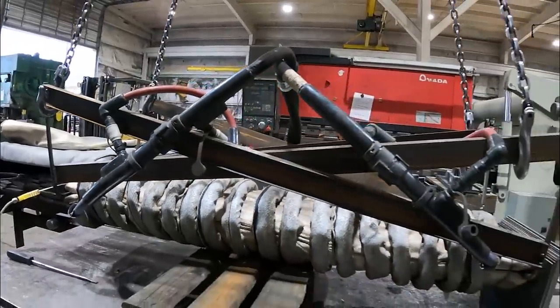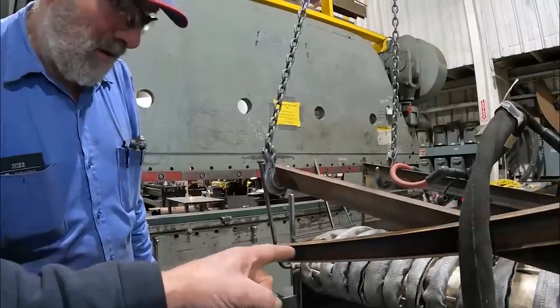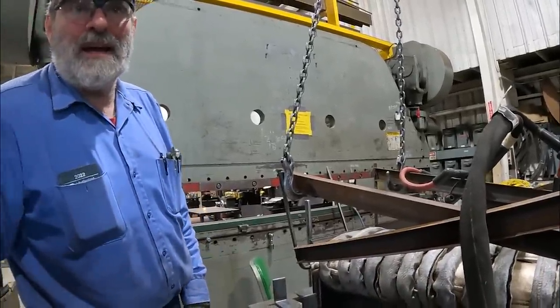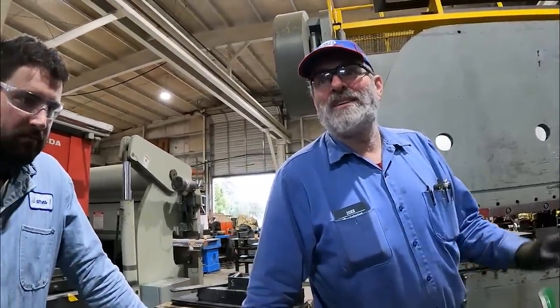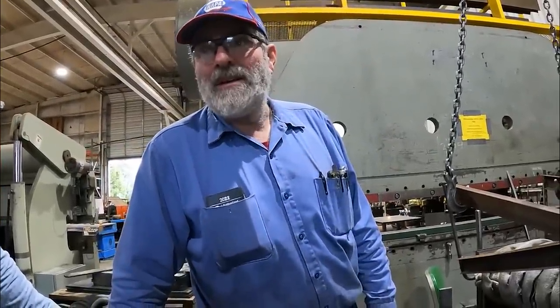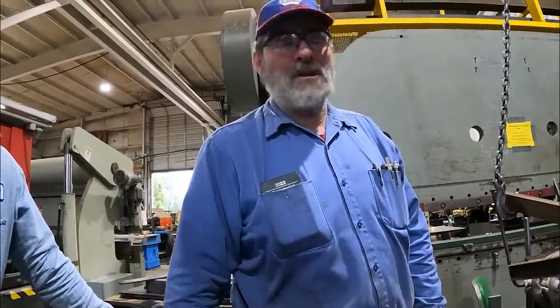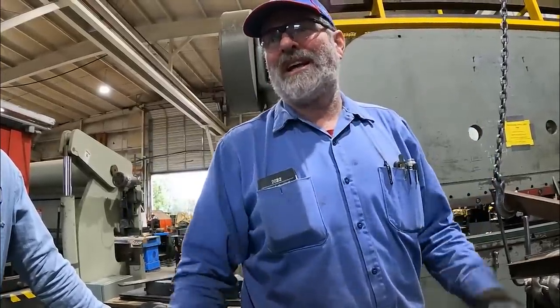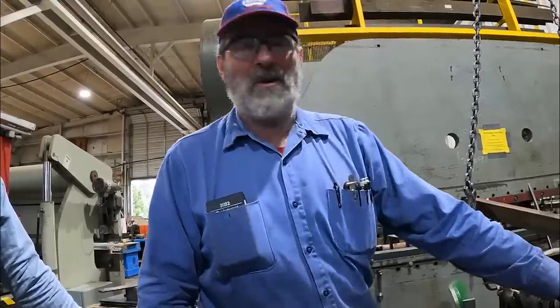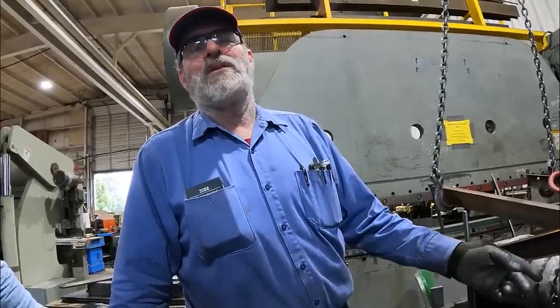Well, you built this? Yes, I built it. I bought an oven from a manufacturer - basically just a flat piece of steel with a coiled-up big snail coil. That snail is the induction element, underneath that big plate. When you heated it, it just warped up - it had stainless on it with a different expansion coefficient. The further away you get from your coil, the less heating you have - it took an hour to heat. So I said forget this - I paid $4,000 for that thing and I made my own. From cold, 15 minutes each compared to an hour each.